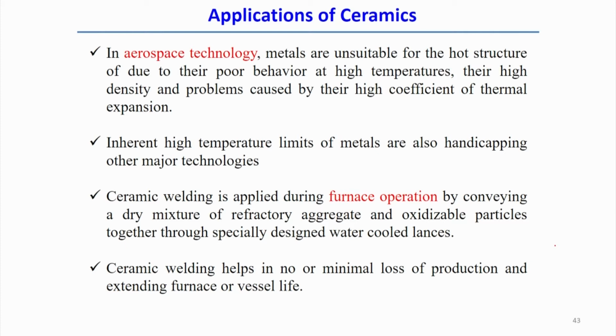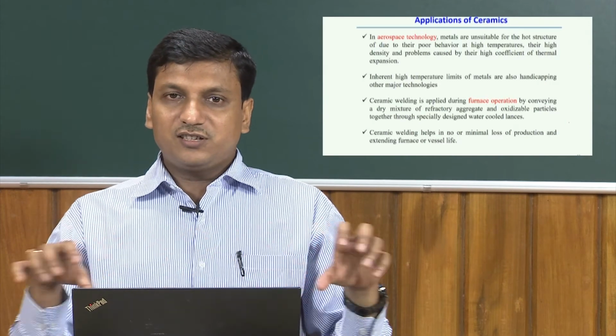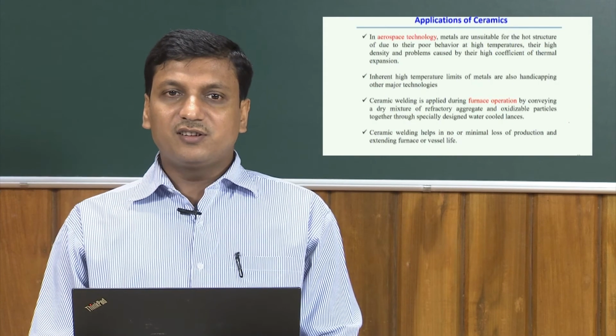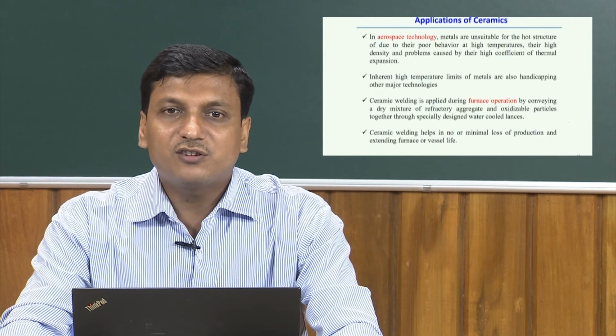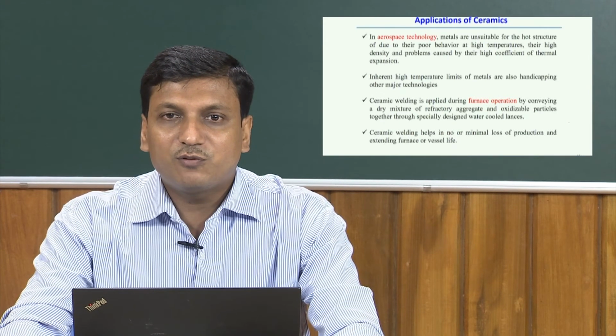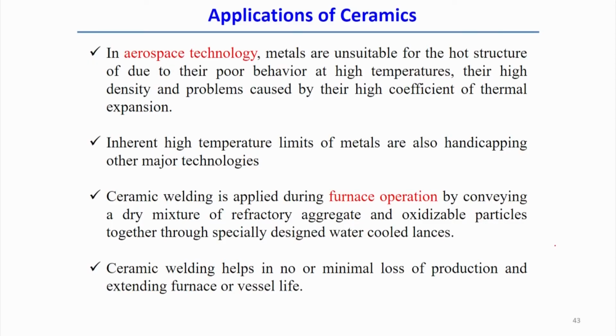Of course, ceramic welding is also applied during furnace operation, simply by conveying a dry mixture of refractory aggregate and oxidizable particles through specially designed water cooled lances. In that channel we can put this ceramic refractory material, and ceramic welding helps with minimal loss of production while extending the furnace or vessel life. So, during the furnace operation, ceramic welding is an efficient way without loss of production, and at the same time it extends the life of the furnace or vessel.